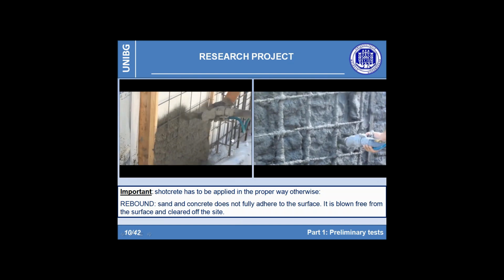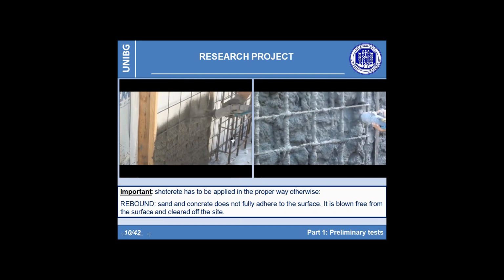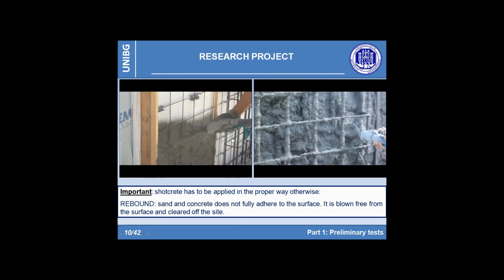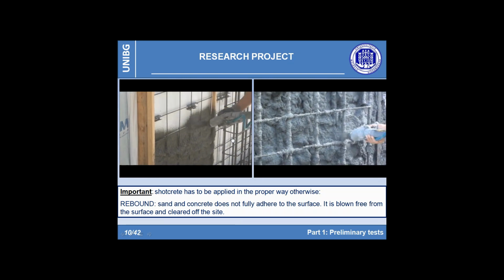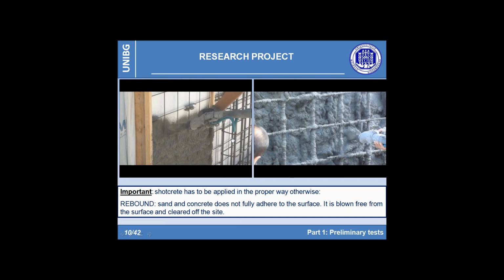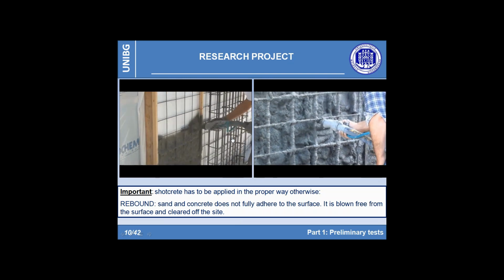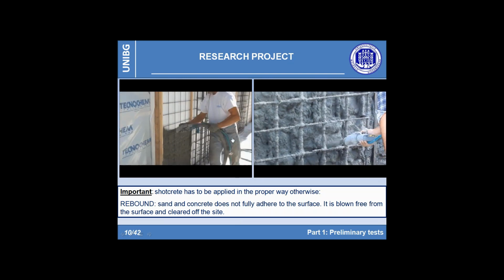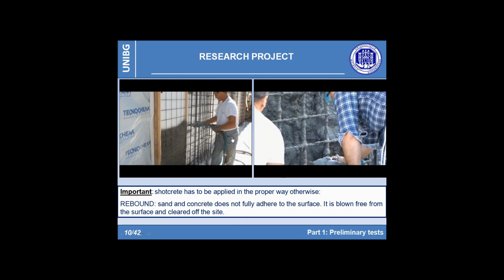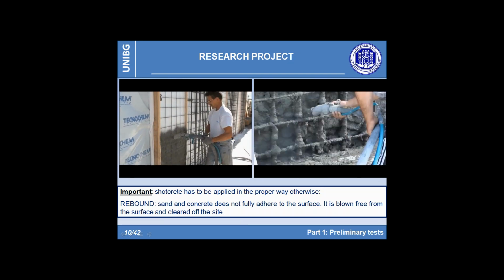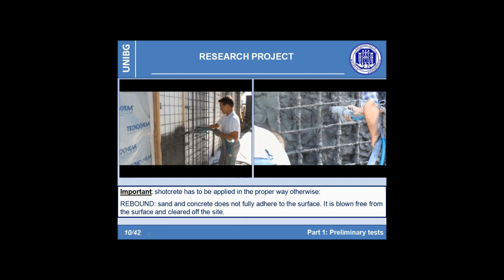In this slide, the shooting phase during the preliminary test is shown. On the left side, one can see the material applied in correspondence of the infill. Instead, on the right side, a structural wall is casted. This is only a first attempt, but the preliminary result gave us important information for the prosecution of the research.